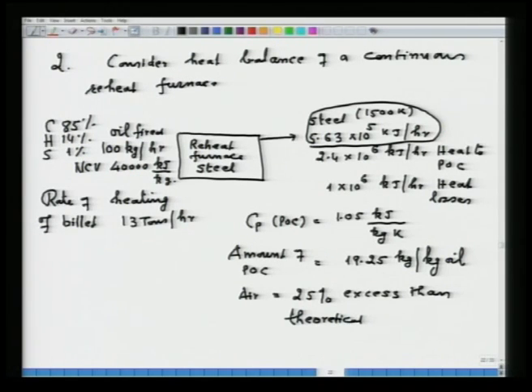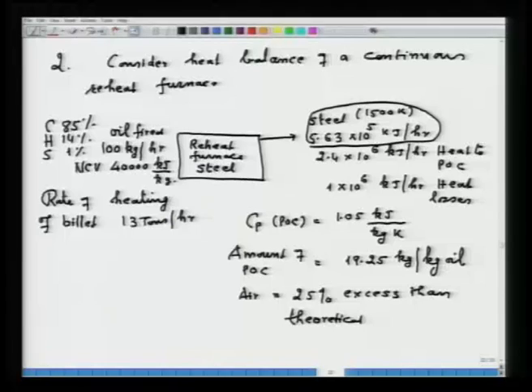My objective here is to show you by calculation in this particular scenario where we are not using any heat recovery, the fuel consumption is 100 kg per hour. Now, again if we see this heat balance, you note that the heat which is taken away by the steel, nothing can be done about it. Only the steel is directly taken to the rolling mill. So, you do not require to again give the heat for rolling purposes, that is one. Heat losses, well, you also cannot do it because it is limited by several parameters, water cooling, opening of the door, through the walls and so on, these also cannot be done.